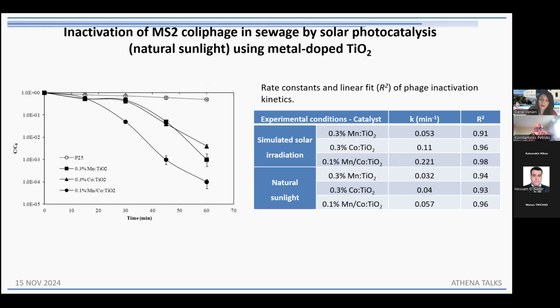And actually, we achieved that result with binary doped catalysts, 2 dopants, manganese and cobalt, during 60 minutes of treatment. Of course, if you see on the right, the rate constants, a linear fit of phage inactivation kinetics, you can see that the rate constants are quite different comparing simulated solar irradiation and natural sunlight. Yes, absolutely. Under natural conditions, the overall process is quite long. Longer periods are required. However, yes, it is a promising result. We can achieve up to 4 orders of magnitude reduction of our virus.